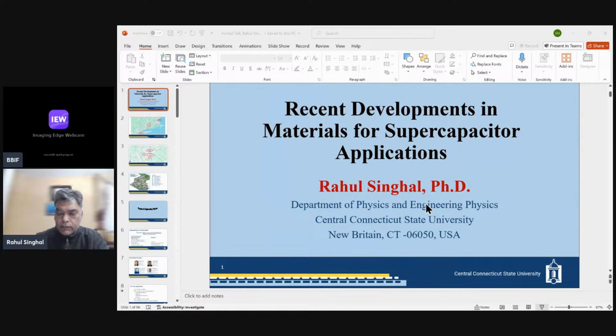As we saw in the TEM picture, with 100 milligram carbon nanotube we have better coverage of the carbon nanotube with MnO2. So we have a smooth surface, or we increase the surface area. That's why it is responsible for the higher specific capacitance with carbon nanotube of 100 milligram. As we increase the carbon nanotube, specific capacitance decreases, which indicates that low carbon nanotube is favorable for increasing the capacitance.